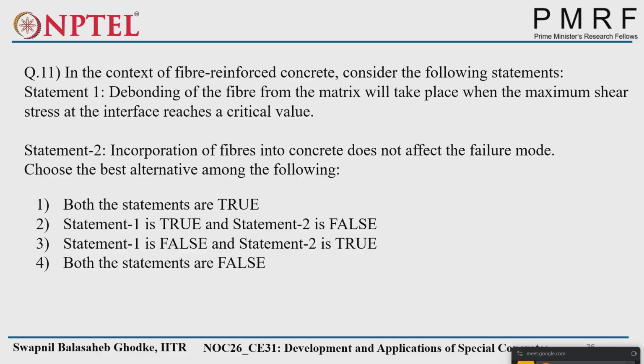Statement 1, you can read it once again. Debonding of the fiber from the matrix will take place when the maximum shear stress at the interface reaches a critical value. It is true because we saw that diagram, right? Embedded length and all those things. If the shear stress around the fiber matrix and the tensile stress are equal, there is a possibility of debonding of the fibers. And the second one is wrong, because incorporation of fibers into concrete does affect the failure mode; it changes the post cracking behavior. Okay. So the first one is true and statement two is false.